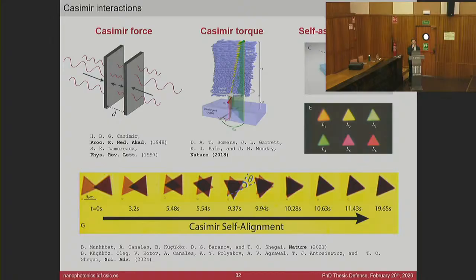There are some ways of including it in a simple way, to derive a lattice sum in the case that you have a mismatch between the substrate and the superstrate. And in this way, you can study effects, as I was mentioning before to Ramón, of how the lattice sum is also degraded in these cases, and the resonances.